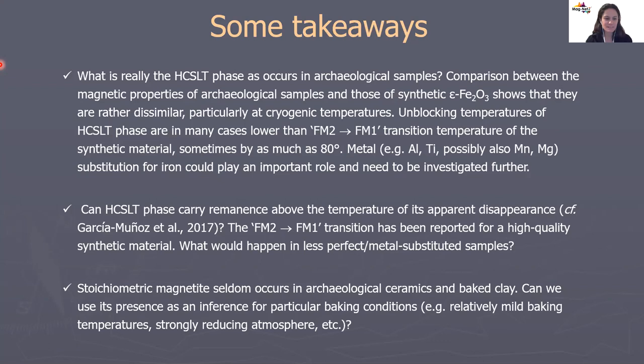Andrei, interesting talk. You know, that epsilon phase must be related to the actual clay composition in the original pot that got fired. And that epsilon phase seems to form from iron-rich smectite clays, from the dehydration of those clays at high temperature. Probably not titanium, but aluminum, calcium might be more important. Yes. Iron substitutions. I agree with that. Yeah. We have to look into it.